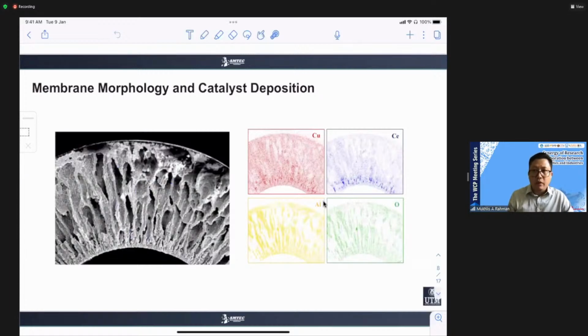So we injected our catalyst inside this. We prepare our own catalyst because we do not want to use catalyst bought from industry or a supplier, because they normally give it to us in powder form or pellet form. The pellet form is not suitable to be used inside this lumen, because you need to crush it first and then pump it, and obviously only a very little amount of catalyst in powder form can enter this lumen. So instead, we use a liquid precursor of the catalyst. Using the sol-gel Pechini method, we prepare that catalyst and inject it inside the finger-like structure. Over here we can see the EDX of our catalyst. This is our base of the catalyst, copper on ceria.